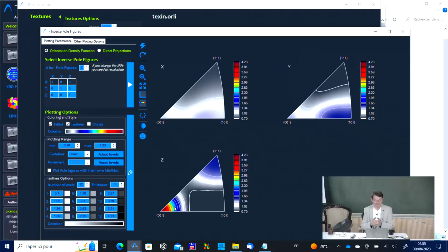So then, in what direction are you going to pull your bar? Of course, in direction Z, because this is the longitudinal direction, this is the axis of symmetry of the distribution itself. So we should then make a tensile testing that certainly, if you want to be coherent with our reference system, in which axis? In direction Z. So yesterday, we were doing simulation on which axis?